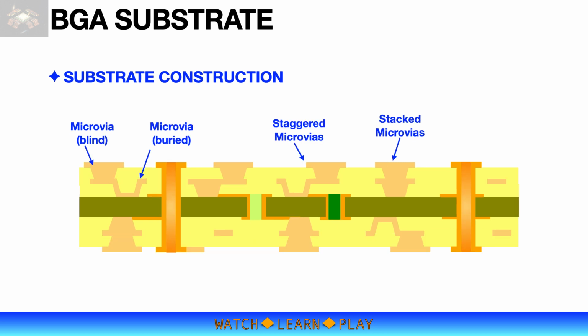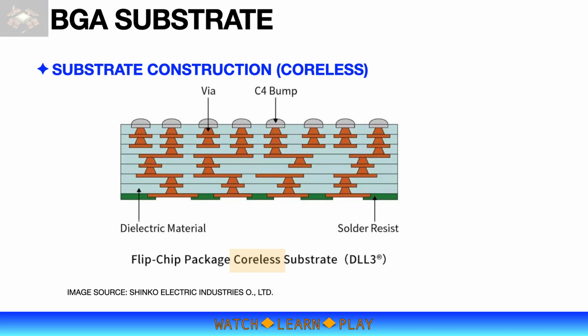Depending on chip or system complexity, more layers are necessary to properly route the signal traces. Additional microvias, blind, buried, and stacked are created within each layer of the substrate. The core adds additional thickness to the substrate. In some applications, vertical space is limited, which means thinner package is required. To achieve a thinner package, the use of a coreless substrate is necessary. A coreless substrate makes connection between layers shorter, thus electrical performance is better. It is, however, prone to warpage, which may affect the package reliability.